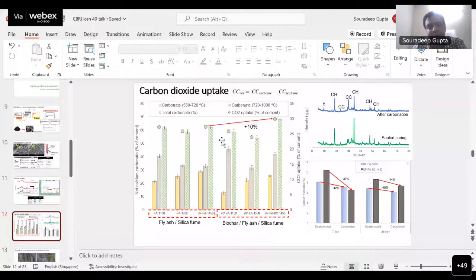Something interesting that has come up here is the distribution of carbonate decomposed at different temperature ranges in thermogravimetric analysis. For example, 550 to 720 degrees corresponds to the decomposition of unstable carbonates, or poorly crystalline carbonates, if I may call it that. Then calcite, which is a more stable form of carbonate, will decompose between 720 and 1000 degrees. Adding biochar shows that the fraction of carbonate contributed by calcite increases compared to the mix without biochar, which is shown by this gray infill bar, right? That is desired because you do not want the unstable carbonates formed from the decomposition of calcium silicate hydrate. Even from the XRD signature, we can see that the peaks associated with calcite have increased substantially after carbonation of the biochar mixed lightweight paste compared to the sealed curing.